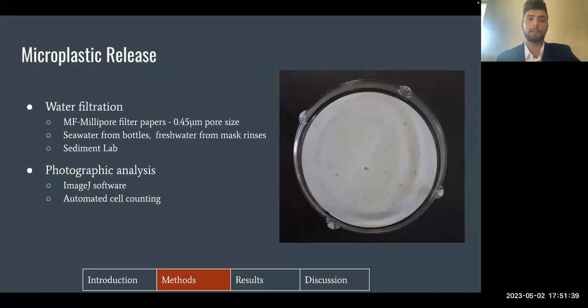I mentioned earlier that the seawater and freshwater used in the experiment was filtered and analyzed. Each portion of water was filtered in the sediment lab with an automatic pump through an MF Millipore filter paper with a 0.45 micrometer pore size and placed into a closable petri dish like the one on the right. Pictures of each filter paper were taken with a high resolution camera and are being analyzed for microfiber counts on ImageJ software. So far, counting each microfiber has been a manual process, but I'm working with the automated cell counting feature of ImageJ to save time and increase efficiency. The picture on the right is from week 1 of the experiment, by the way.